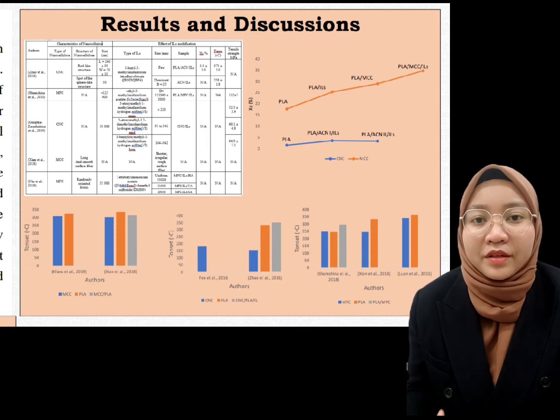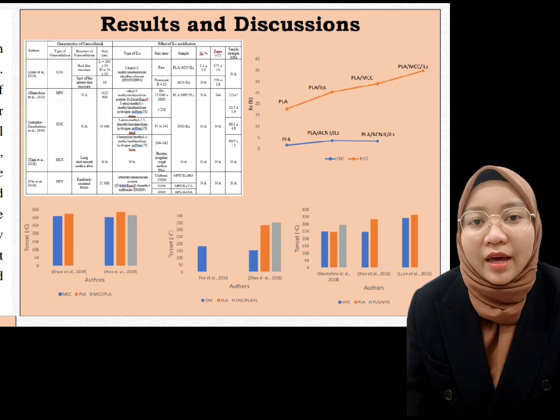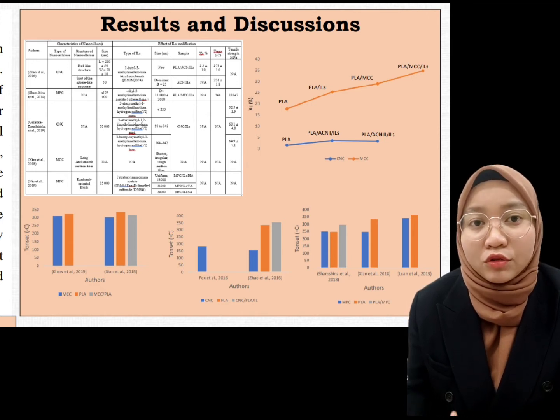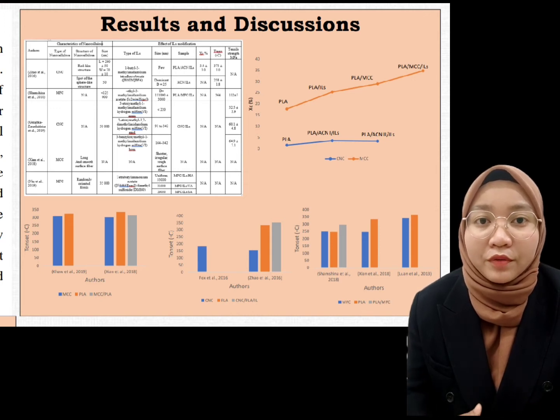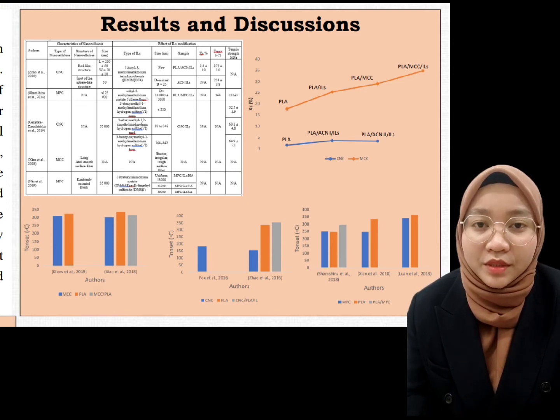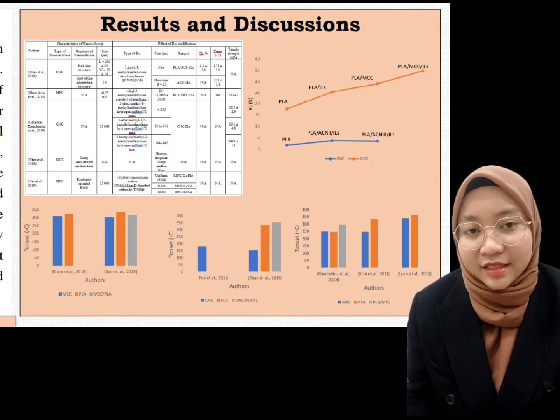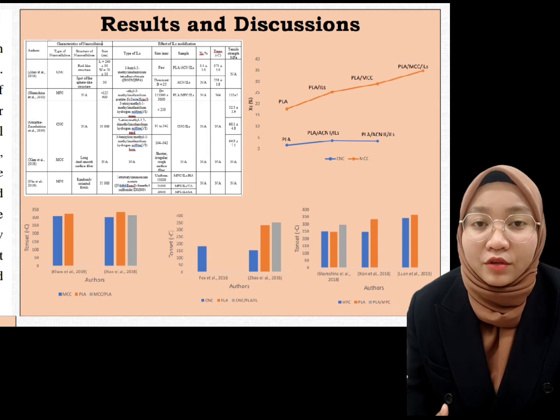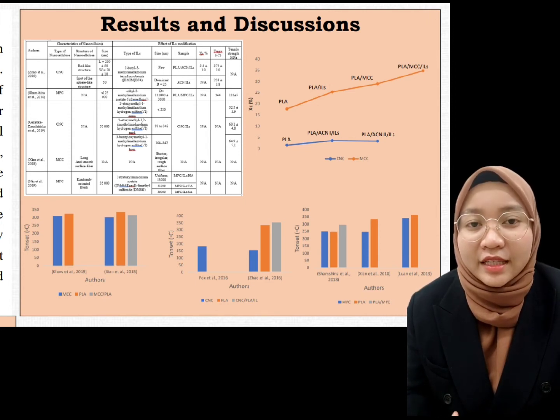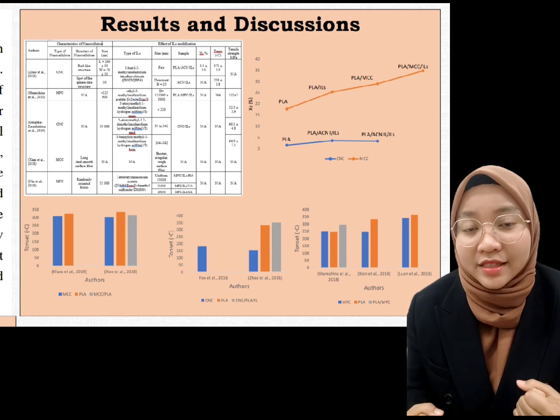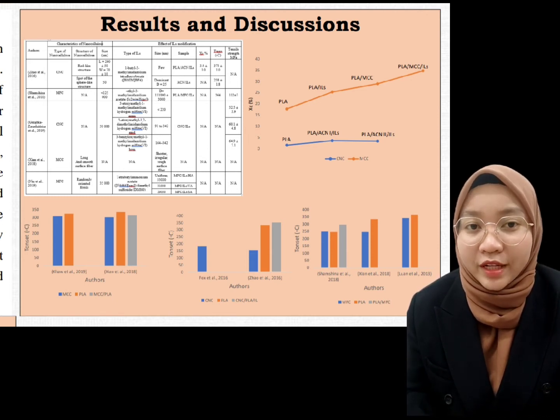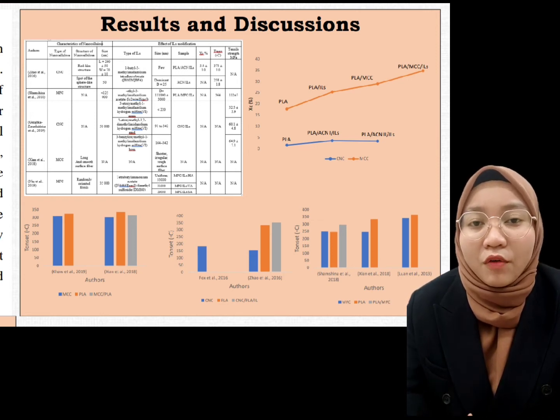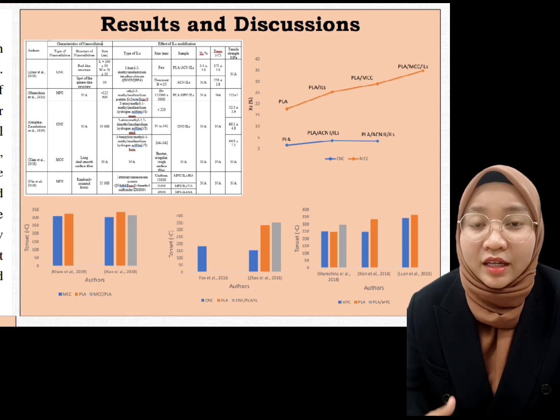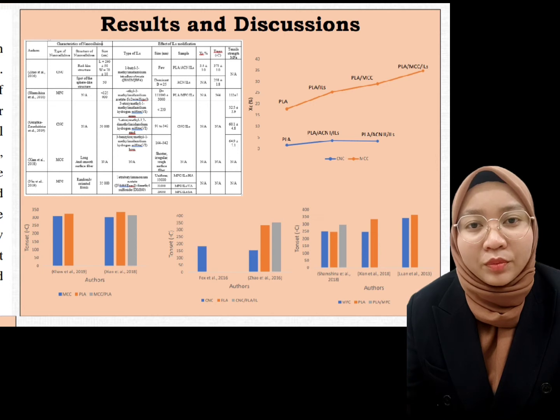So in comparison to MFC, the size of regenerated MCC reinforced with PLA is reduced, and 0.006 to 0.052 was the smallest. Because of the increased specific surface area of the reinforcements, composite have improved characteristic. The incorporation of nano reinforcement is strongly advised. The interaction between weak hydrophilic PLA polymer and strong hydrophilic NC was weaker than less hydrophilic NC. The modification of ionic liquid gives the positive impact to the nanocellulose. It will become less hydrophilic.